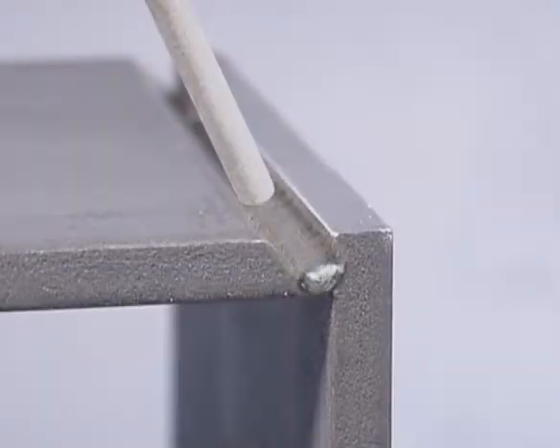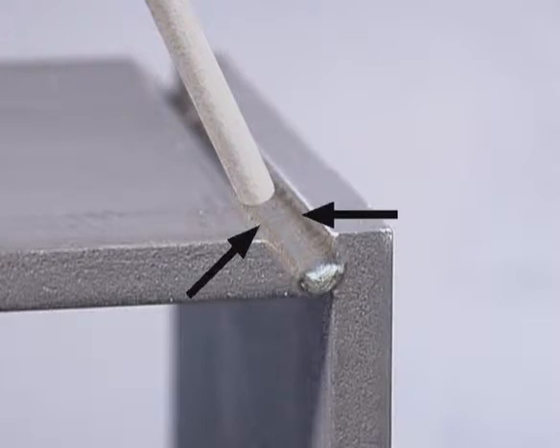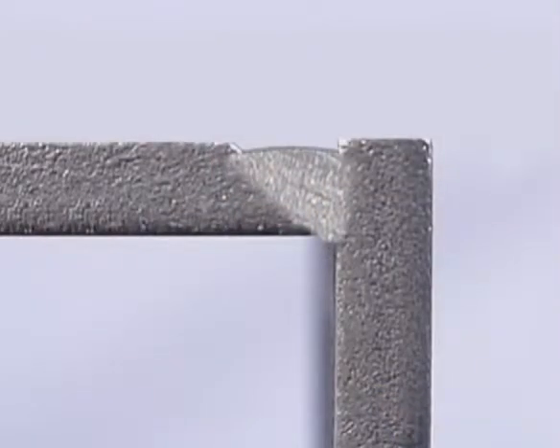Angle the rod into the joint, making sure the puddle flows out and ties into both pieces. A first pass of 6010 or 6011 will provide good penetration and is easier to handle in the bottom of the joint. With 7018, try using a 3/32 diameter rod for the first pass, especially in the horizontal or vertical weld position. Keep the top of the filler beads flat to avoid trapping slag and leave the top edges as guides for the cap.